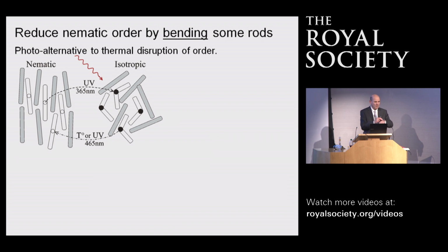I mean, we know them in that they produce color for our clothes, but dyes absorb light and they can change the structure. So these guests, when they bend, destroy the order of the hosts, and we've gone, in a sense, from the cold ordered state to the disordered state, not by putting heat on, but by putting light on.